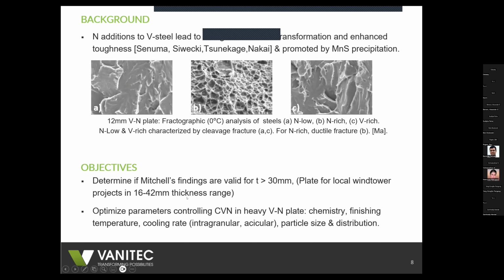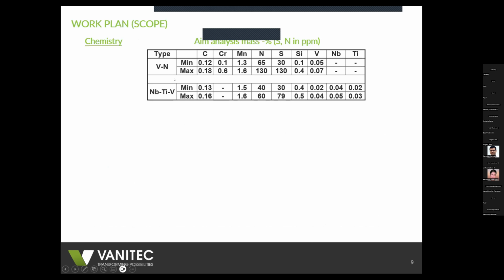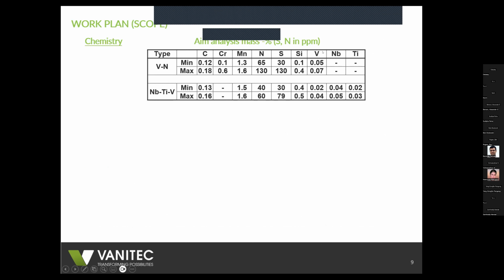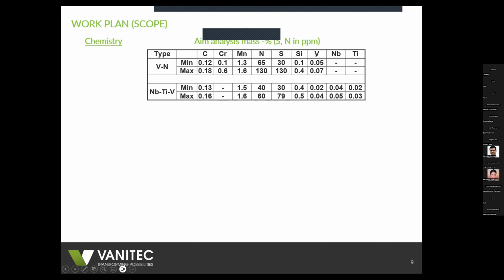So on the academic side, we would like to optimize these parameters controlling Charpy toughness in heavy vanadium nitrogen plate. We want to see what the influence of chemistry, finishing temperature, cooling rates, and particle size and distribution have on toughness. Chemistry, the scope would be vanadium nitrogen steel with those typical limits over there, 65 to 130 nitrogen and 0.07 vanadium, and then compare that with either vanadium titanium only or vanadium titanium with a little bit of niobium steel in it, grades of which we currently have.